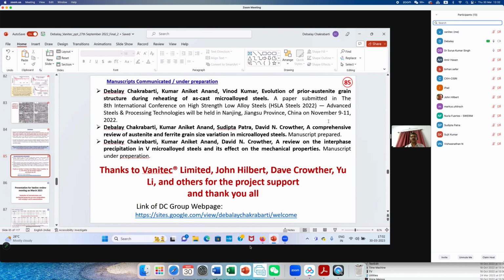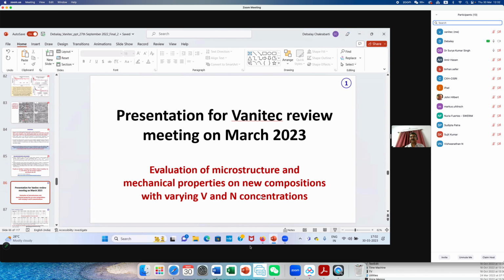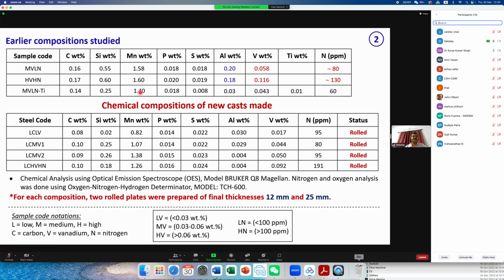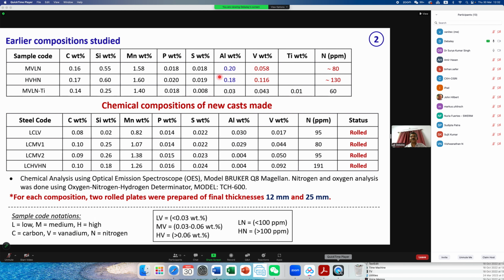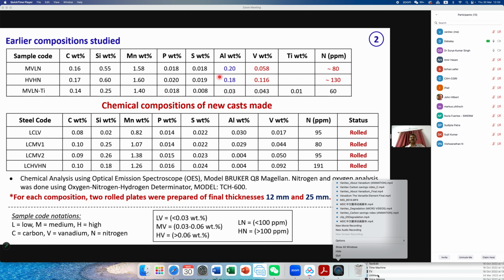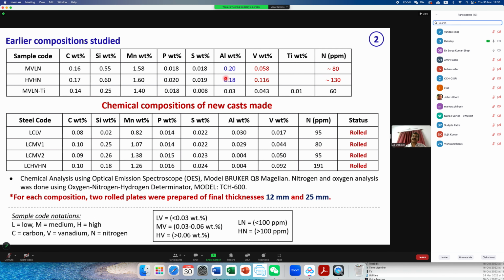With this, I come to this presentation for March 2023. I am quickly going through whatever we have achieved. Previously we made 3 grades. You may remember that out of those, 2 grades we were not happy with because we could not control aluminium. So aluminium nitride was forming instead of vanadium nitride, and vanadium was in solution. We were getting a bainitic microstructure. So these kinds of problems happen. In the 3rd grade, we managed to control aluminium, so we got good properties, E350 properties. Subsequently, we melted 4 compositions. We had a little bit of an issue with carbon content.